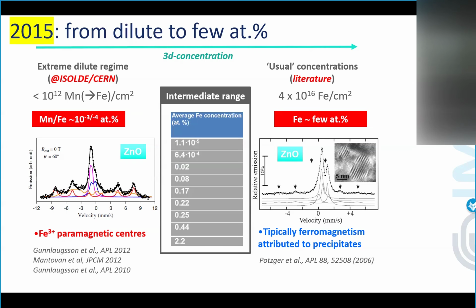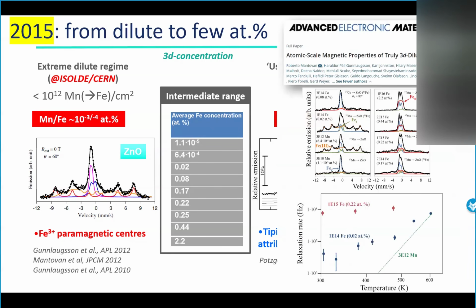To do that, we prepared a set of samples by making pre-implantations in the lab and then implanting at CERN. So we scanned basically all the range from the ultra-dilute regime up to a few %, which is what I like to call the literature concentration typically used. And these are the results, okay? What I anticipated here is the relaxation rate that we extract from the broadening of the lines. And in the ultra-dilute regime, we are somewhere there.